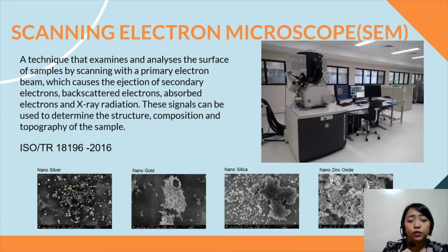Scanning electron microscope, or SEM, is a technique that examines and analyzes the surface of a sample by scanning with a primary electron beam, which causes the ejection of secondary electrons, backscattered electrons, absorbed electrons, and X-ray radiation. These signals can be used to determine the structure, composition, and the topography of your sample.